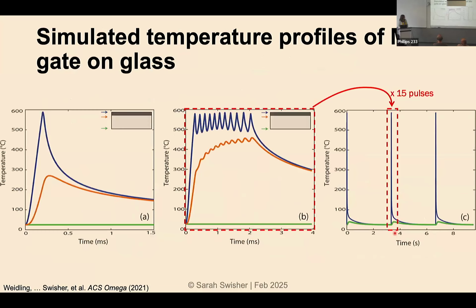If you do that, the tool that we use has incredible precise definition of the time that the lamp is on and off, so that we can do what's called micropulsing. So we can do a single pulse where the lamp turns on, the temperature comes up, and then when the lamp turns off, it comes back down again. And what we're showing with these different colors is the temperature at the top surface, just below the metal interface in the substrate, and at the back of the substrate. So again, that green line is basically showing you that you're barely heating the back part of that substrate. But you certainly are heating up right below the metal.